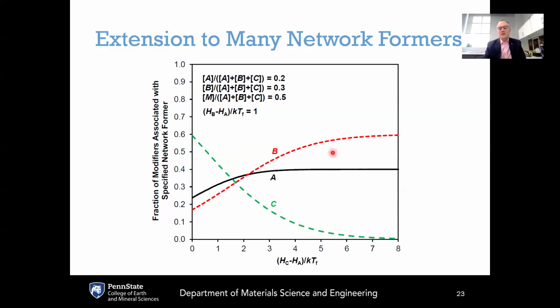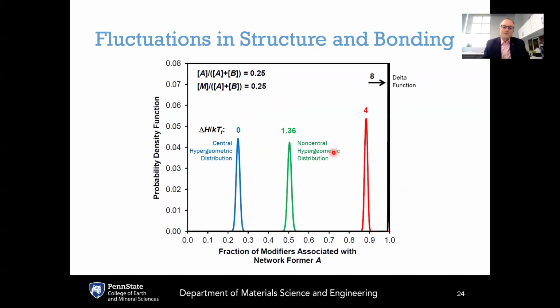And you can see here in this plot that it is a function of both the chemistry of the glass, in terms of the molar concentrations of each species, as well as the energetic differences. And you can have different regimes where different network formers are either more preferred or less preferred.